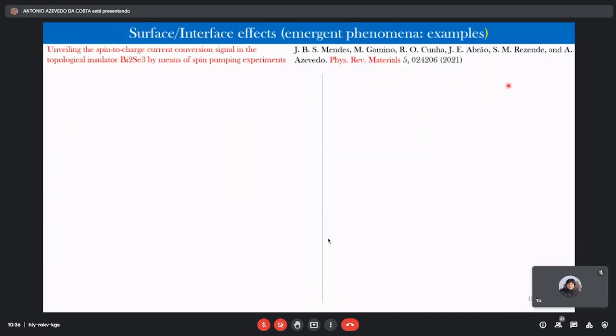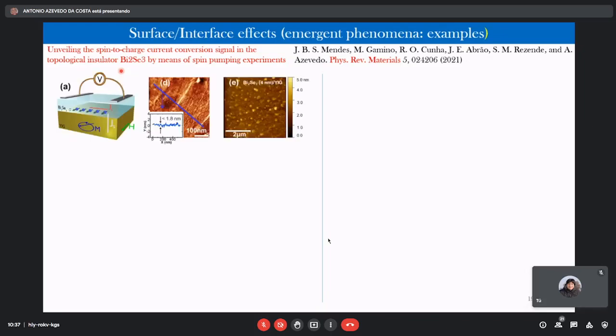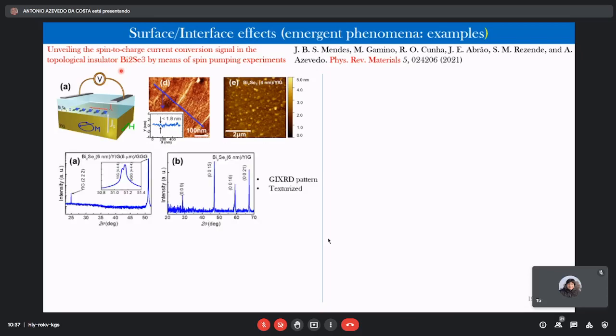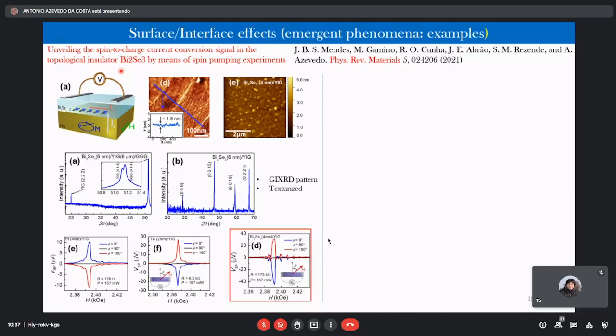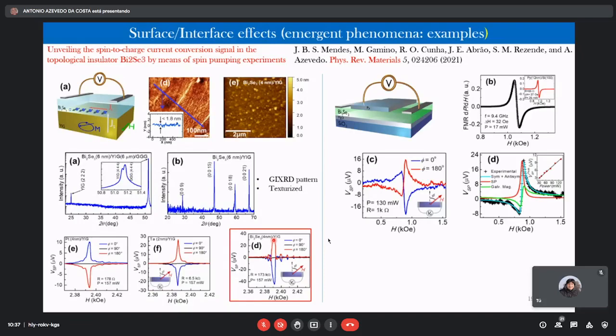And more recently, we published some papers in which we also deposited this material, which is considered a topological insulator, by sputtering, and we also measured that even when deposited by sputtering, it conserves these topological insulator properties, which conducts at the surfaces and is an insulator in the bulk. So we made the X-ray characterization, and we detected that in this case, this material converts the spin to charge with the opposite sign as platinum. For instance, platinum converts spin to charge with a positive spin Hall angle. Tantalum has a negative spin Hall angle, and Bi2Se3 has the same sign as tantalum. We published this paper last year, and we made several measurements.